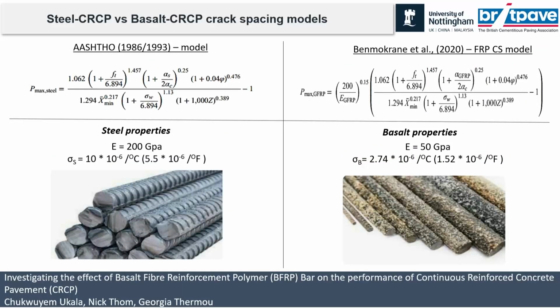So now we know how steel performs. We decided to test how FRP bar performs. And currently, as I said, there are no real standards for basalt bar. But Benmokrane, in collaboration with the Department of Quebec, Canada, developed something calibrated using glass FRP. He used the same equation as for the steel, and he just included a factor that takes into account the Young modulus of the FRP. So the 200 there is the 200 gigapascal Young modulus of steel, divided by the Young modulus of the FRP. He used glass, and his model shows that this represents more of what we will get in the behavior of the